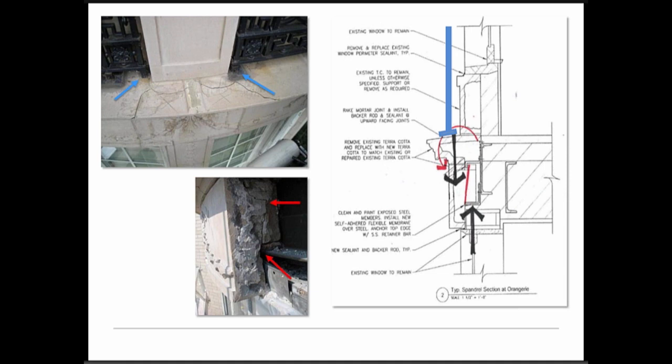Other causes of distress include railings bearing directly on terracotta, putting undue stress on units not designed for that load. Lintel units that are notched out — either in manufacturing or by the contractor on site — create weak spots where stresses build up, resulting in cracking through the unit right from its support point, all due to the weight of the railing on top.